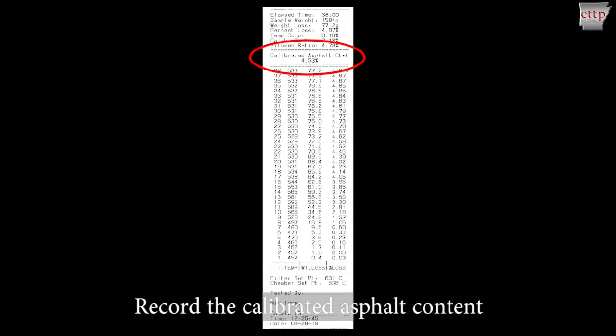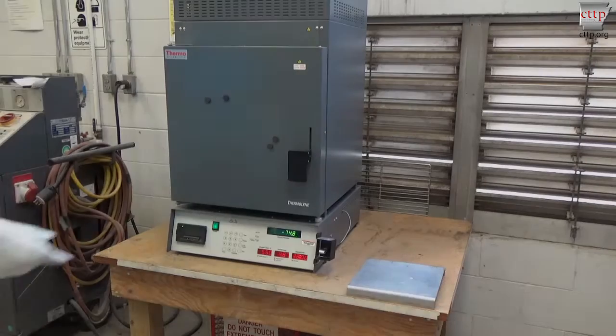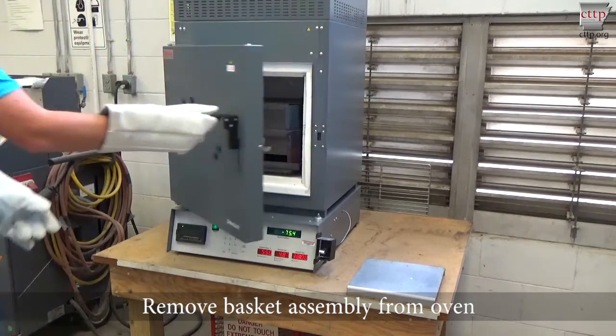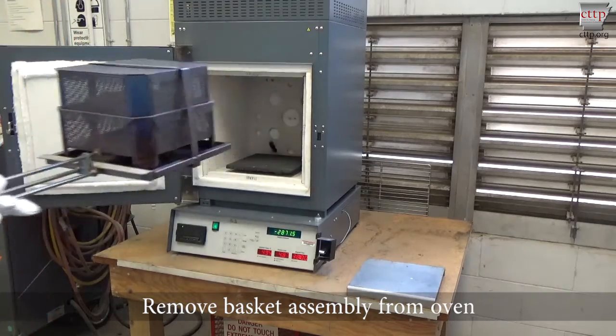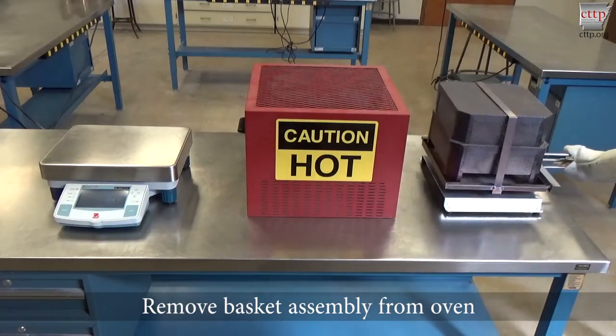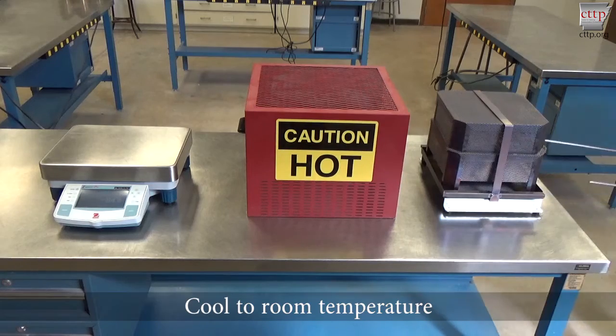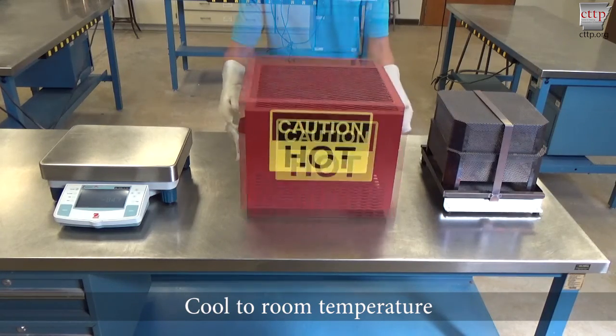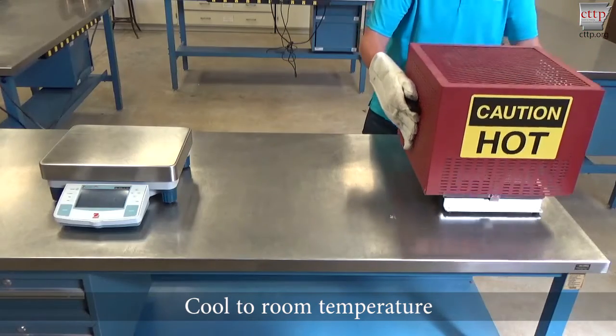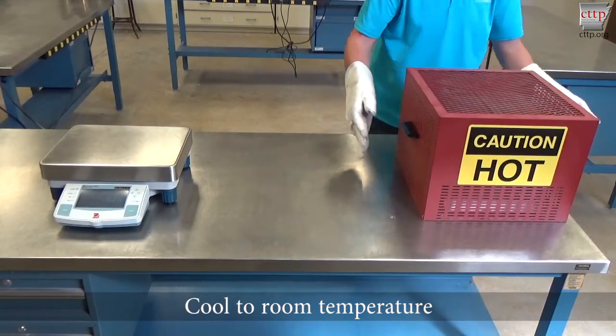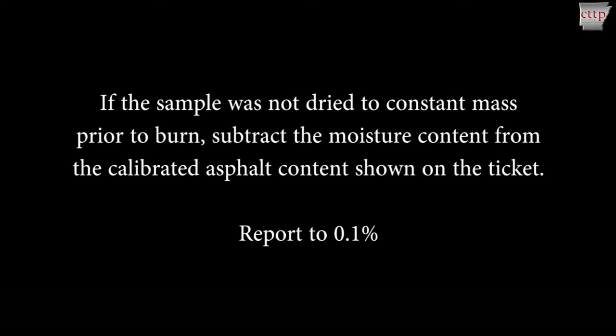Record the calibrated asphalt content from the ticket to the nearest 0.01%. Remove the basket assembly from the ignition furnace with the loading fork. Place the basket assembly on a heat-resistant surface capable of withstanding 1,202 degrees Fahrenheit. Cover with a protective shield and allow the basket and aggregate to cool to room temperature. If the sample was not dried to constant mass prior to burning, subtract the moisture content from the calibrated asphalt content shown on the ticket. Report the binder content to the nearest 0.1%.